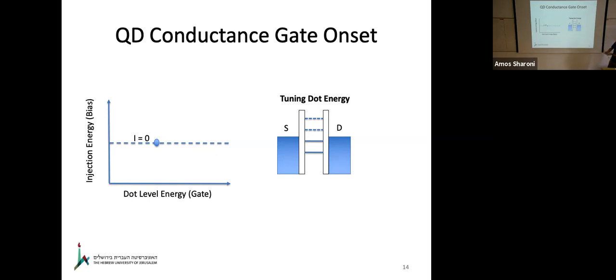What you have is the following situation. You look at the gate, which is an electrode tuning these energy levels up and down, and you look at the bias, which is tuning the source versus the drain, and you ask whether or not you have current. Now, you can tune the gate, reach this resonant condition, and this means that now in this bias versus gate space, you're going to have current exactly at this gate level. But you can further tune the gate and you tune into the Coulomb regime again. So you lose your current. If you sweep the gate here, you're going to see an onset and offset of electrical current.